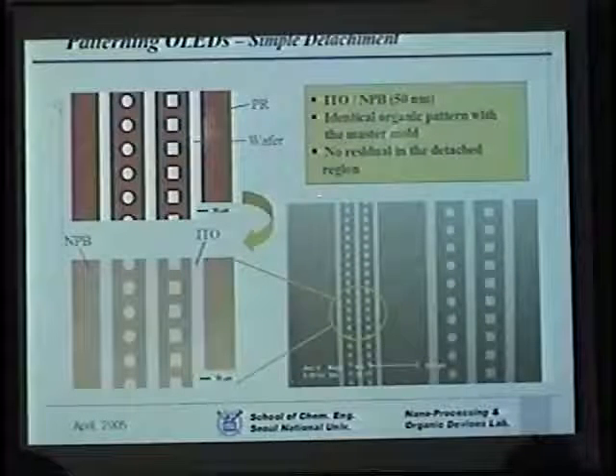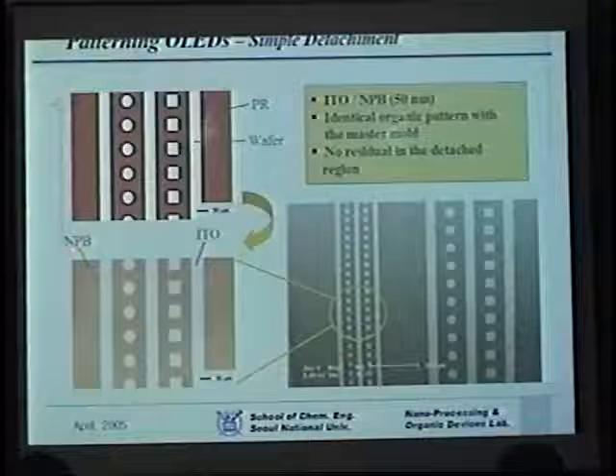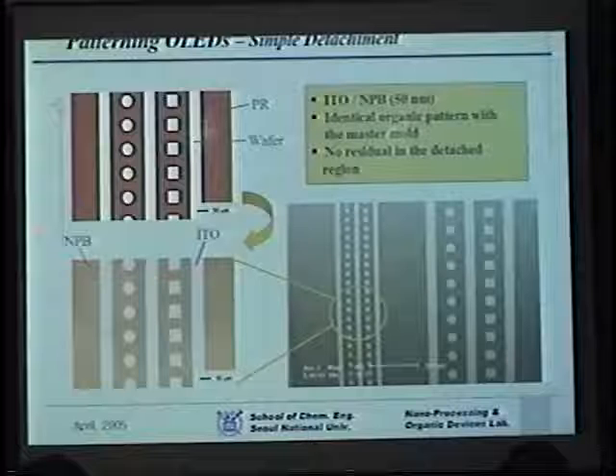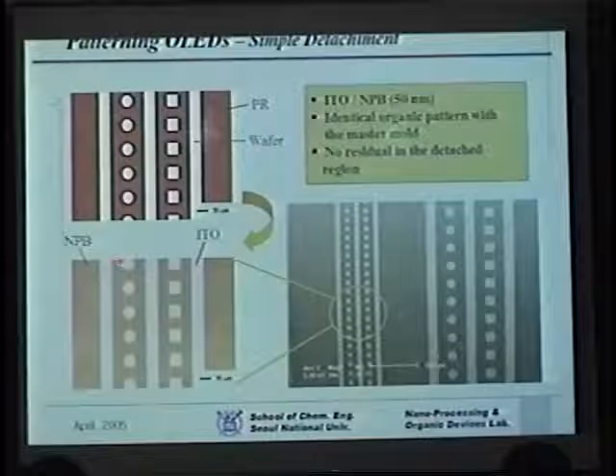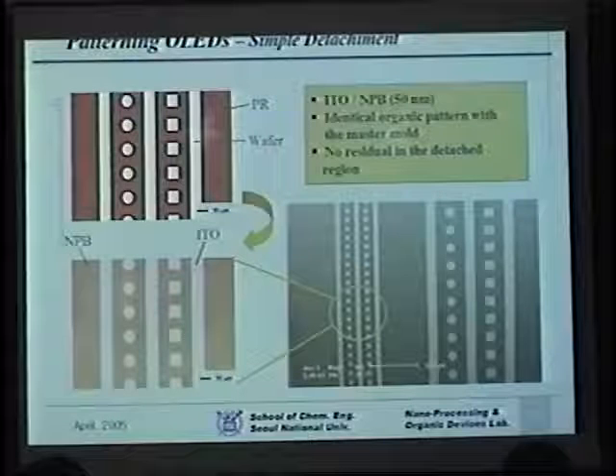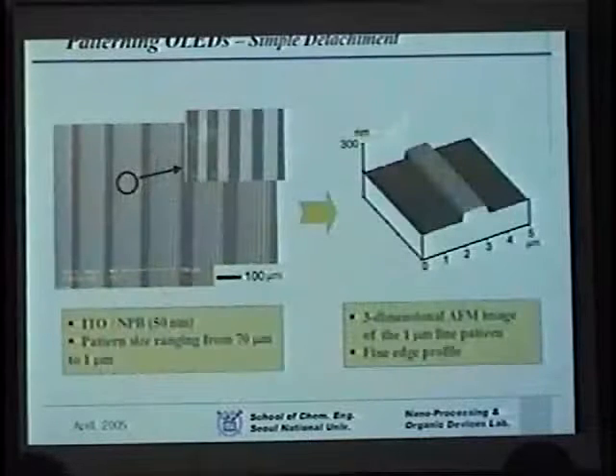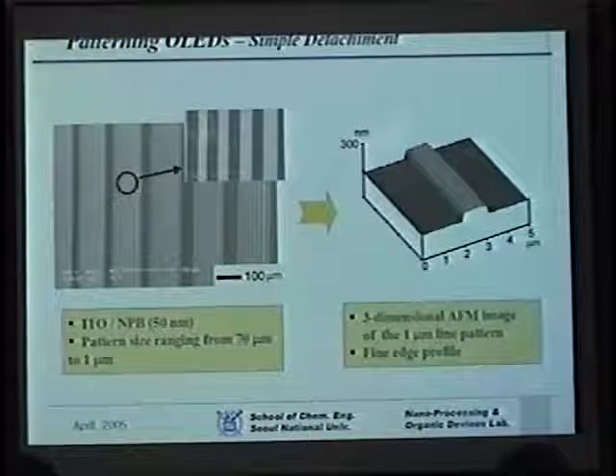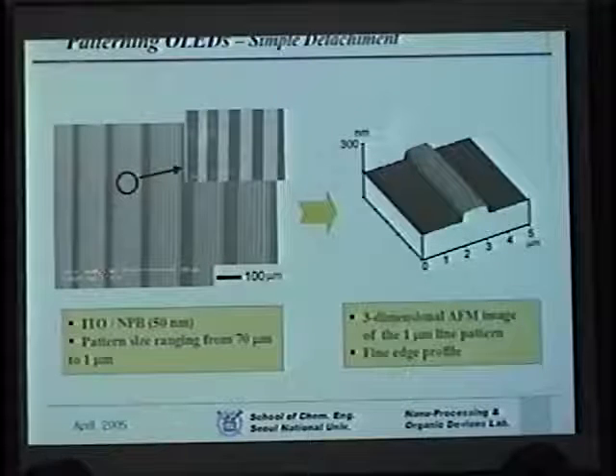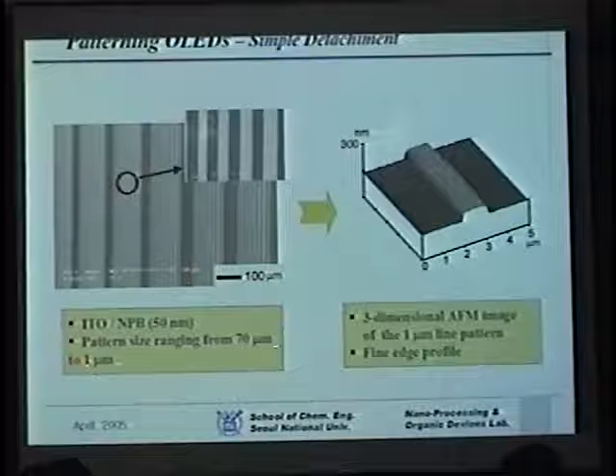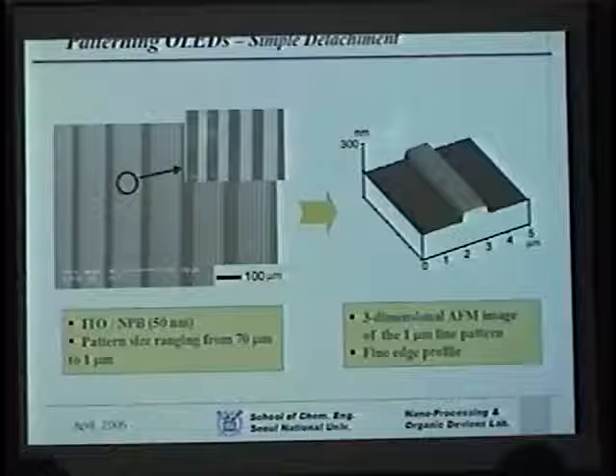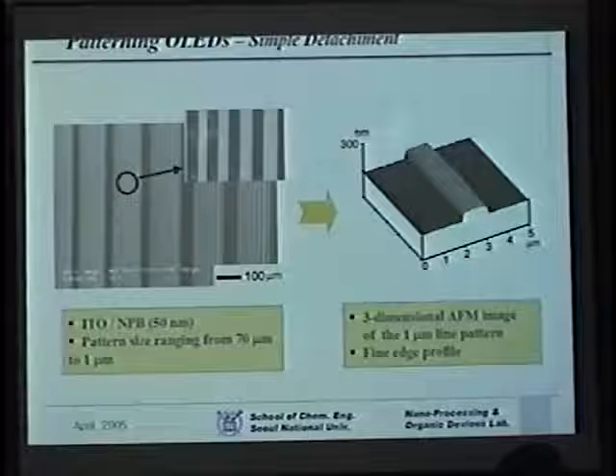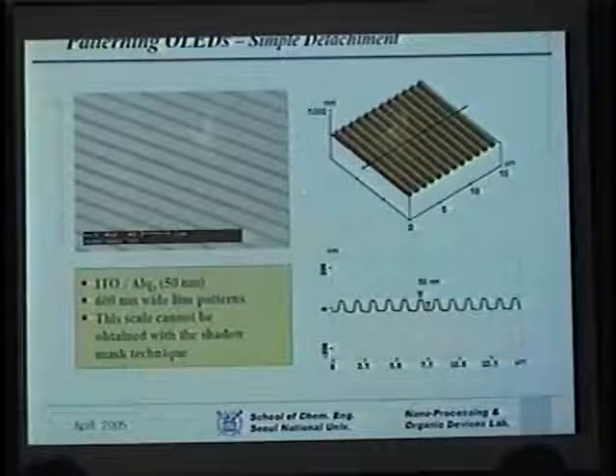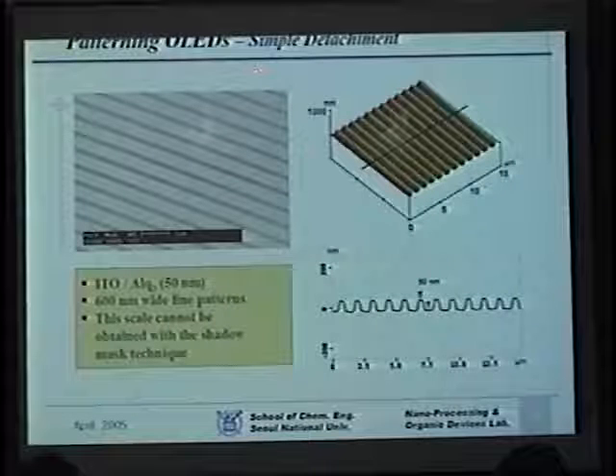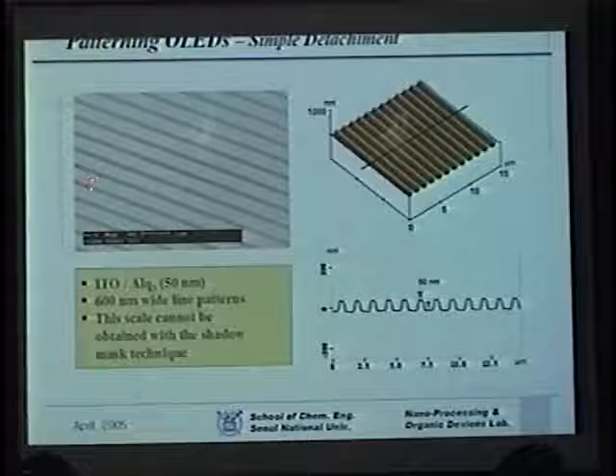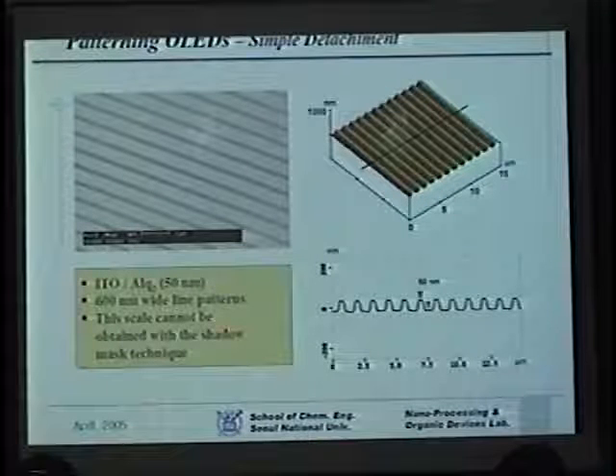So to show that it is effective, we did some actual patterning here. We had an NPB layer on ITO coated glass, NPB being the hole transport layer. And we could see that the patterning can be done fairly well. Also we wanted to show that the method is equally effective when you have a series of lines with different size, in this case from 1 micron to 70 micron. And we also wanted to see the edge fidelity, and you can see the fidelity is not that bad. Here is another example of patterning done through the simple detachment method. Shown here are 600 nanometer lines. Of course, these kinds of lines cannot be defined by the shadow mask technique.